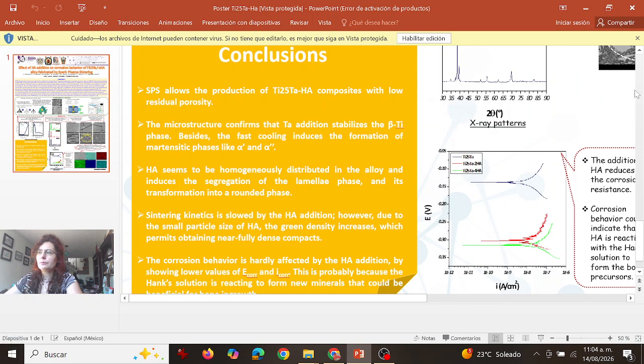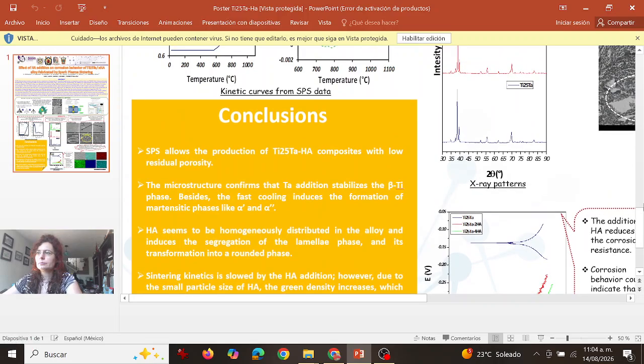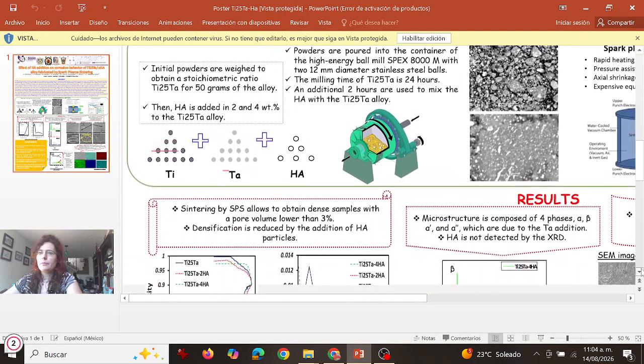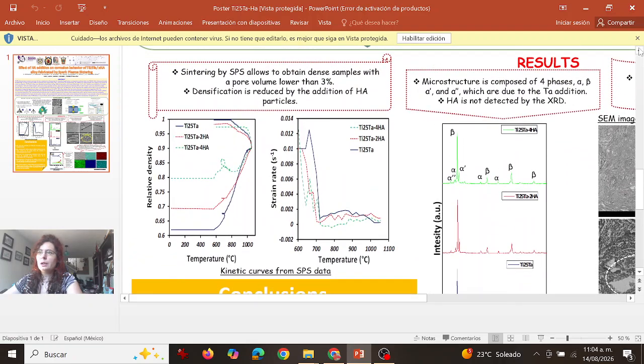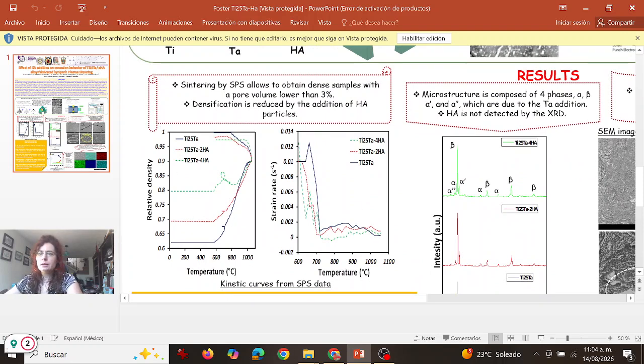Let's continue with the results. For the first part of the results, we are going to have a look at the kinetic curves from the SPS data, from the Spark Plasma Sintering machine. Here we have two curves. One is the relative density versus temperature in degrees Celsius, and the other one is the strain rate versus temperature. For the two graphs, we have three curves. This one in black corresponds to the titanium-25 tantalum alloy. In red, we have the curve for the titanium-25 tantalum with 2% of hydroxyapatite, and the green one is for the titanium-25 tantalum with 4% of hydroxyapatite.